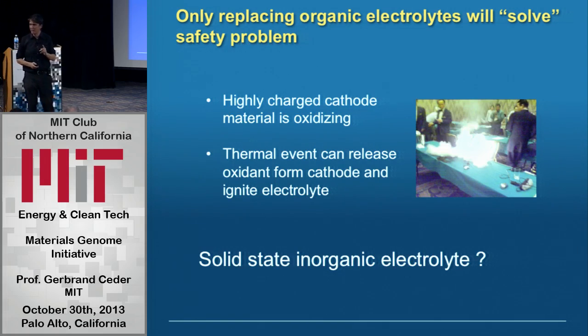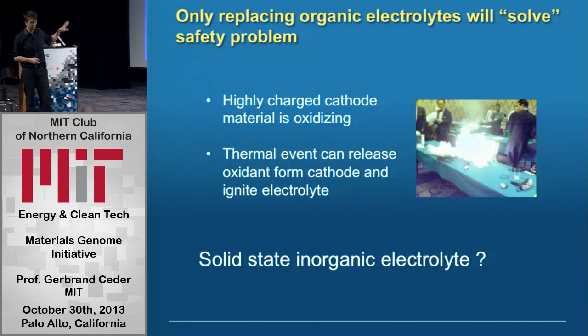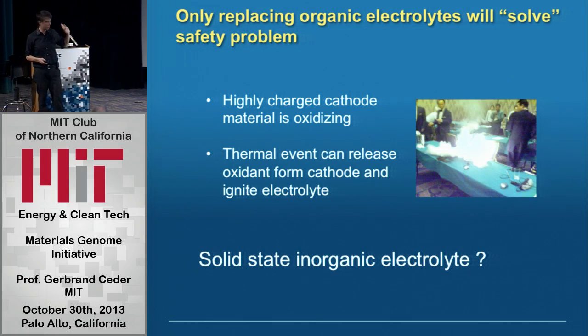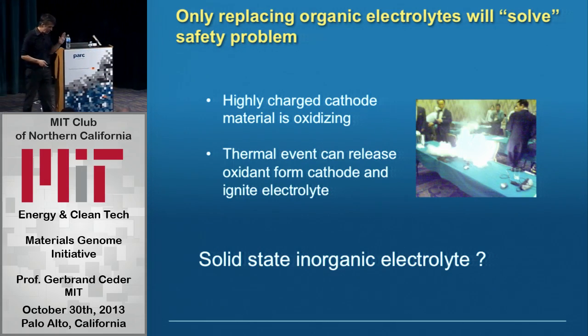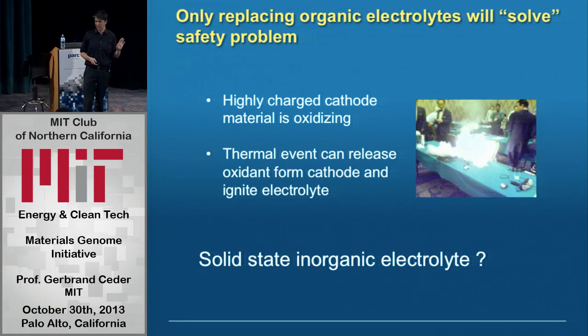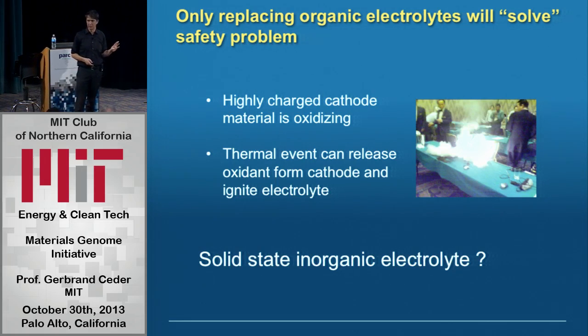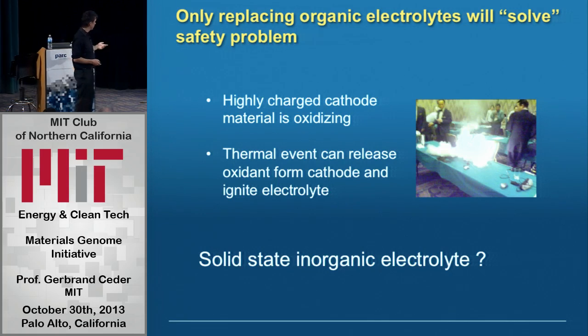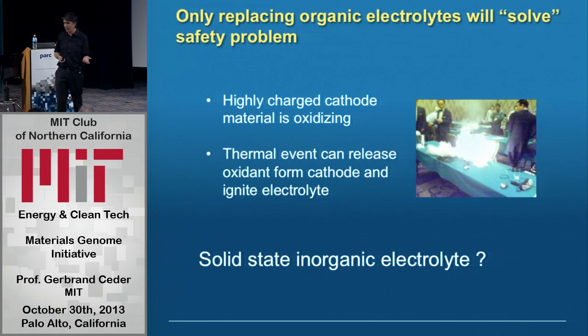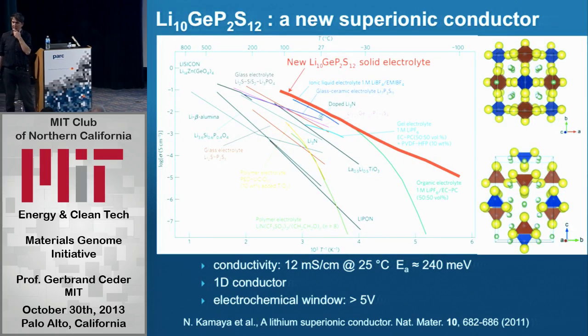A lot of that can be mitigated. But the problem of electrolyte leaking and spilling fire is a lot harder to deal with. So in my opinion, the only way we would be able to completely get rid of this problem, and we're not totally sure this is possible, is by going to non-combustible electrolytes. The only ones so far that have come close to working are complete solid-state electrolytes. Can you make a solid, inorganic electrolyte that is a really fast lithium-ion conductor, so you can put it in a battery between the electrodes? And we thought the answer was no.